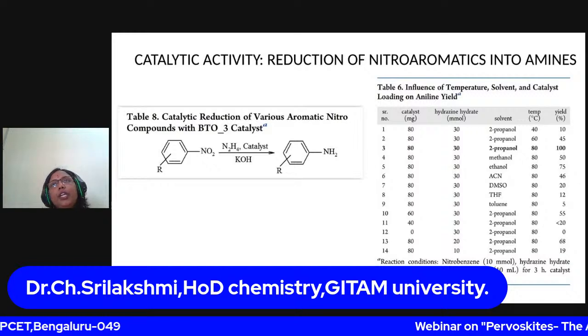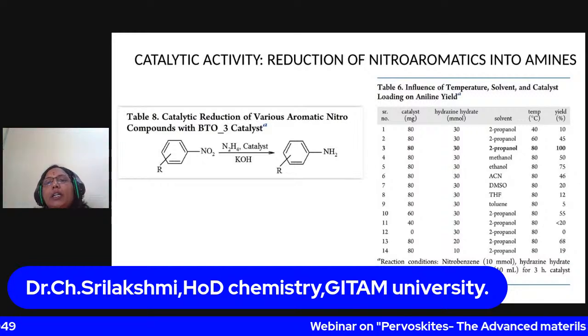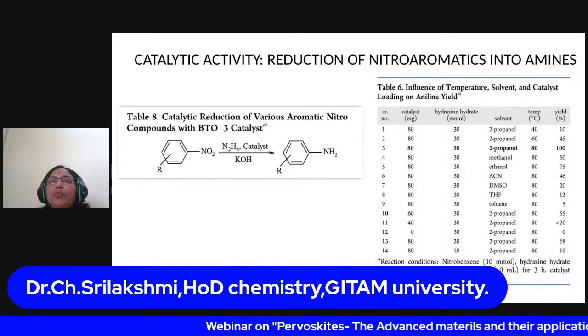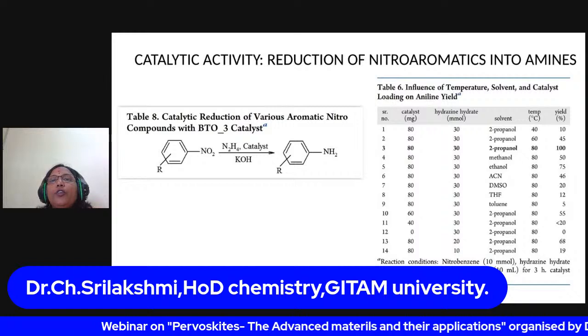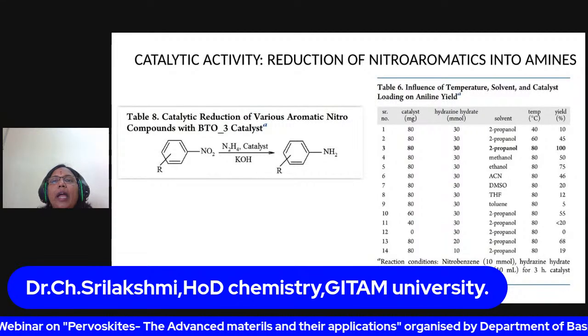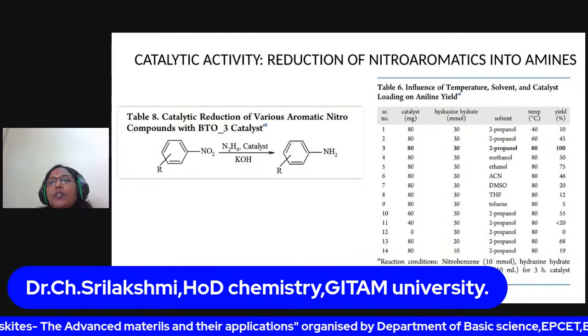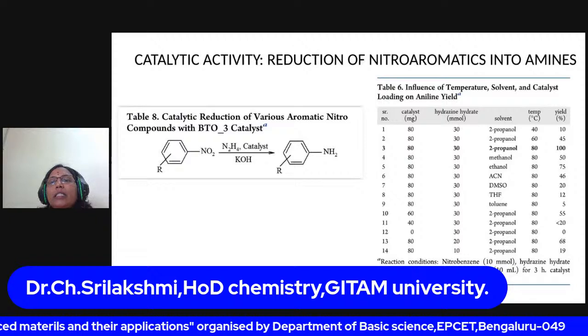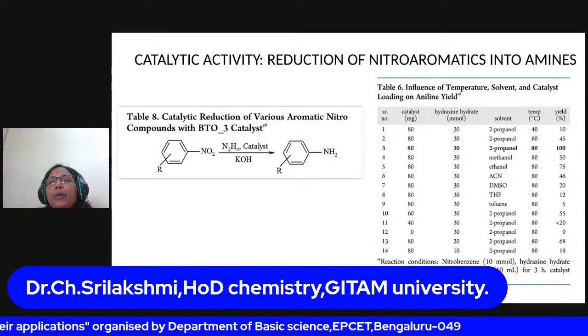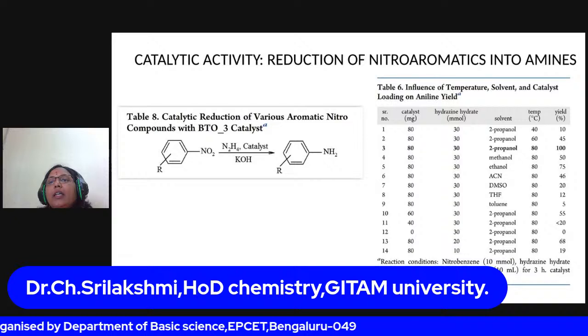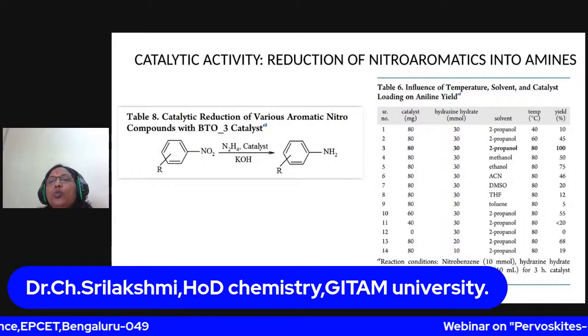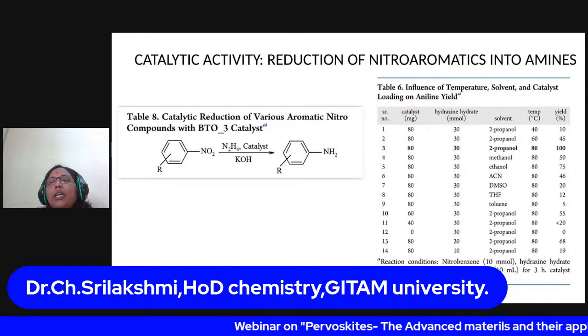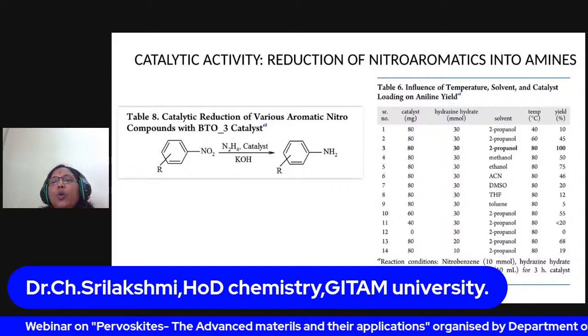Before proceeding with this reaction, we need to optimize the reaction conditions. How can we do that? You need to see the influence of temperature, solvent, and catalyst. With these optimized conditions, we understood that a temperature of 80 degrees is suitable to obtain 100% yield, 2-propanol is the best solvent, and 80 mg is the optimum catalyst loading to achieve good yields.